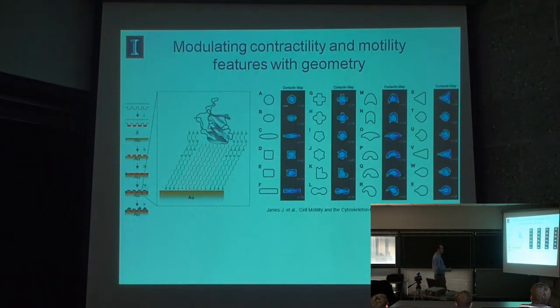The platform we use to do this is microcontact printing on thin layers of gold. We like gold because it's such a well-developed chemistry for self-assembled monolayers. In essence, we make a PDMS stamp, just a regular silicone rubber stamp. We can ink that with a chemistry of choice. In this case, we use this octadecanethiol molecule, which can chemisorb to the gold surface and form a very stable gold-sulfur bond. Then by patterning that, we can backfill the remaining regions outside with a non-adherent oligoethylene glycol moiety, which will prevent protein adsorption and cell adhesion. We can then physisorb to the surface of these hydrophobic regions some protein of interest. We usually use fibronectin, but we've also looked at laminins and collagens. Because we have these ethylene glycol regions, we can capture cells specifically on the islands that we stamped.